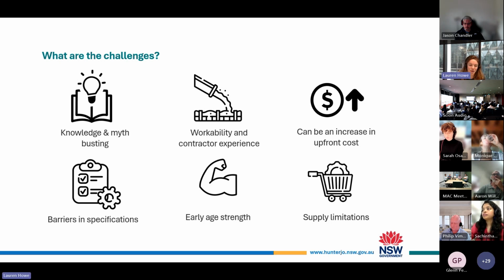In terms of early age strength, using cement replacement does increase the curing time that is required to reach your 28-day strength. And so a number of years ago, 5-10 years ago, this was the reason why low carbon concrete generally wasn't being used, but there have been a lot of advances in technologies around use of different admixtures that then allow for the same high early age strength to be met if that is something that is needed for your project. What we've found often is that actually the project doesn't need a high early age strength, but if it does, then there are mixes that the suppliers can provide that will achieve those same strength requirements at the early age.